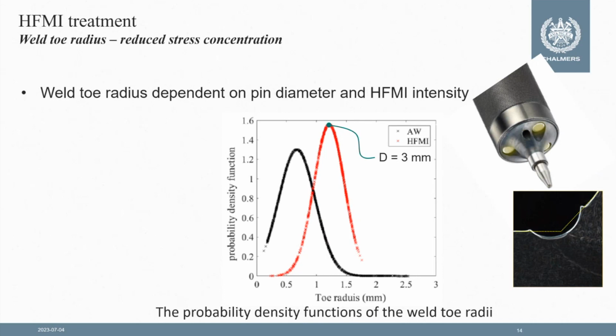The transition at the weld toe region and the radius that we get there will also depend on the pin radius or pin diameter. You see here the measured toe radius from as-welded and HFMI-treated details when the HFMI treatment was done with a pin with a diameter of 3 millimeters. The mean value of the radius lies around 1.5 millimeters.